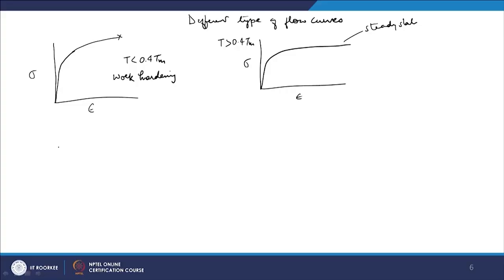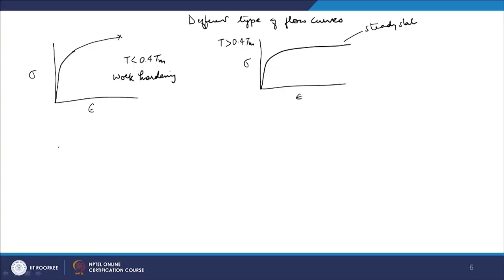So what is that mechanism? Because we are deforming at a temperature more than 0.4 TM here. Now other microstructural processes will start, and one of them is called dislocation recovery, and the dislocation recovery is helped by the vacancy concentration in the material. You must be knowing that equilibrium vacancy concentration of a material increases exponentially with temperature. So you may increase temperature linearly, but the vacancy concentration will increase exponentially, and these vacancies help the dislocation in the recovery process. The actual mechanism is dislocation climb. So dislocation recovery takes place. The number of dislocations which are generating, the same number of dislocations are getting recovered. Because of that you get a steady state deformation.